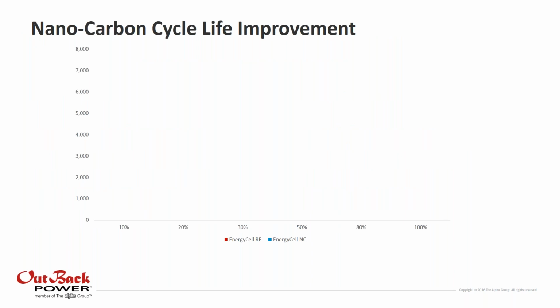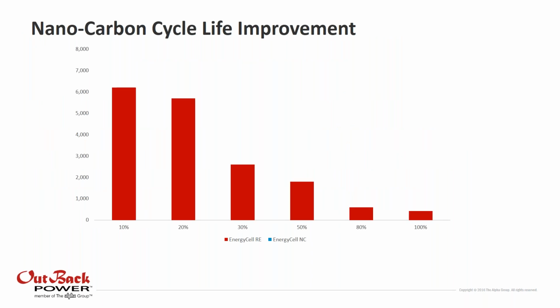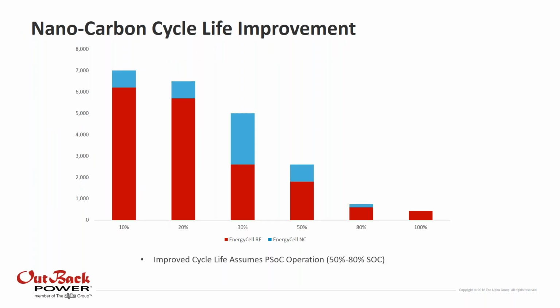And here, it's just a graph talking about what we just went over. So you can see here, this is the RE cycle life at 10% depth of discharge, all the way down to 100% depth of discharge. And the blue is the cycle life improvement you'd see with Nano Carbon, again, assuming you're operating in 50 to 80% state of charge with a 100% charge every month or 2 weeks. Where you really see the biggest jump, as you can see, is the 30% depth of discharge range. You see almost a doubling in the cycles that you'll get with a Nano Carbon battery than you would with an AGM battery. So that's a really nice place to operate these batteries.